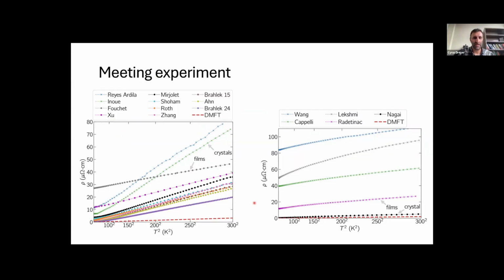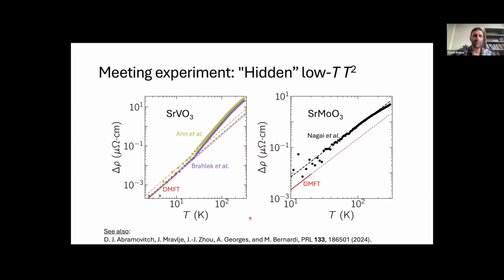of the measurements. But if we zoom in to the low resistivity regime and just consider a selection of these measurements that have extremely low residual resistivity, then we see an interesting behavior. This is accentuated in strontium vanadate and also pointed out in this previous paper, that there's actually two T-squared regimes in this material. There's one that goes up to about 30 Kelvin, and then there's another one at higher temperature. And our DMFT calculation actually matches fairly well, within those error bars that I mentioned, the low T-squared regime.